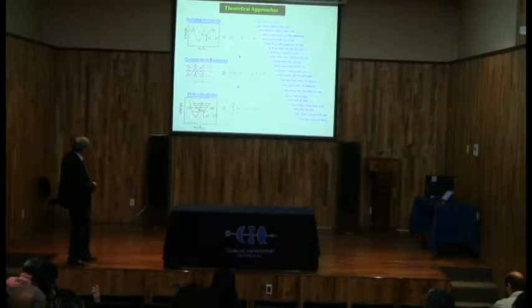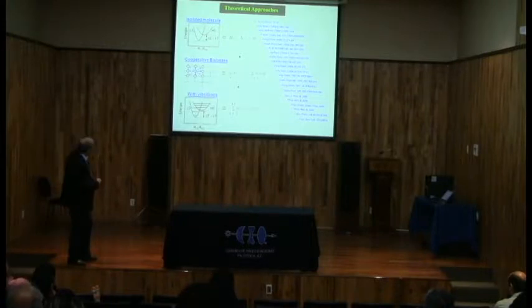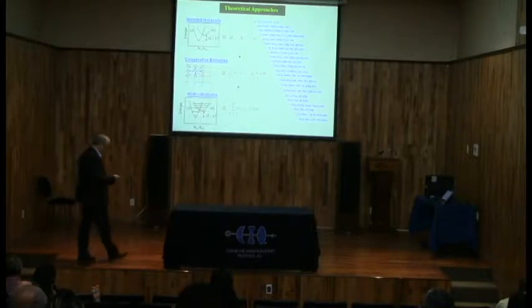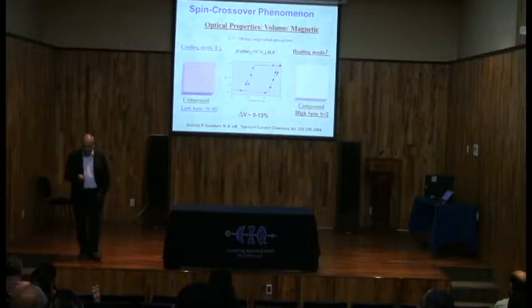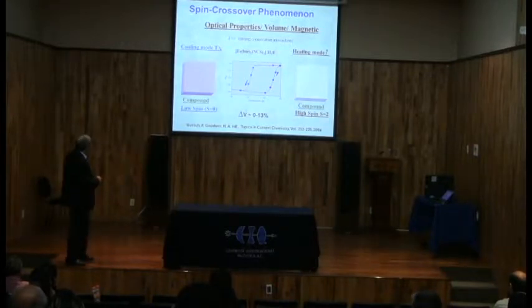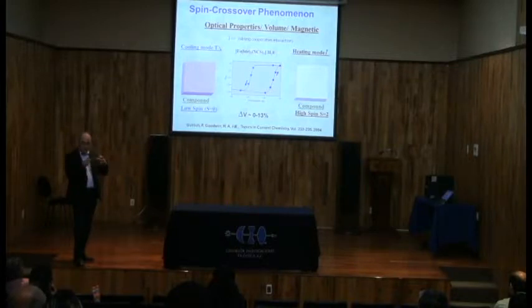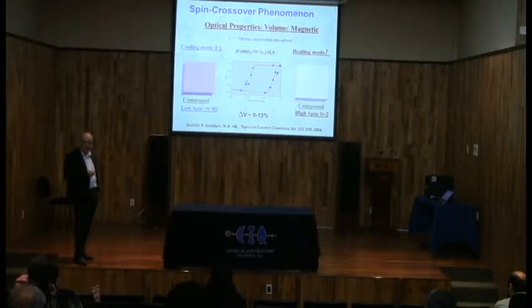And then, of course, when you go from one state to the other one, the volume of the molecules changes, so you have to add the vibrational properties of each state. So the spin crossover system is just the addition of these three terms, these three energies, and then you can describe your system by this methodology. So if we take an example, for example this molecule here, we have strong cooperative interactions. I mean that we have strong elastic coupling between molecules. If you have such a case and you try to solve your Hamiltonian, you will find that you have a first order phase transition in this system.